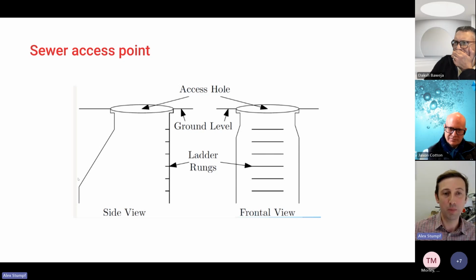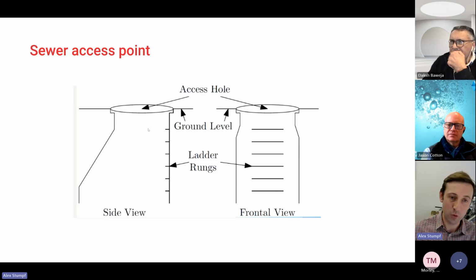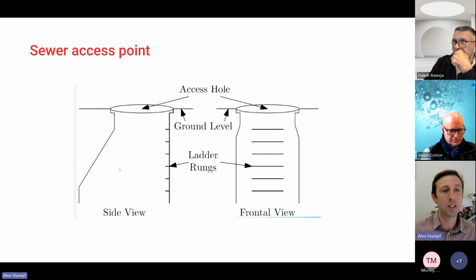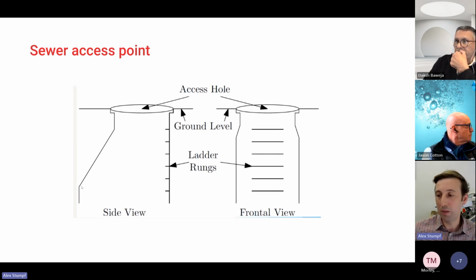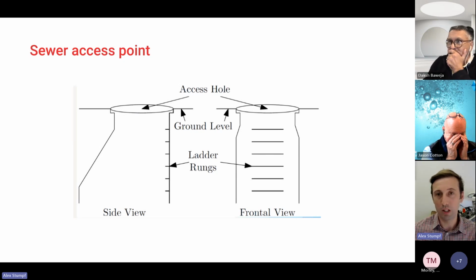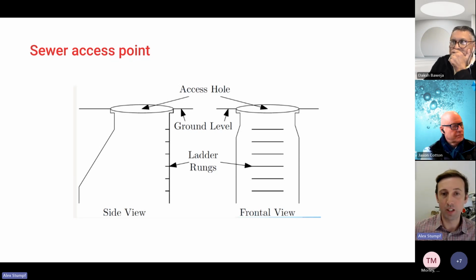So this is what a sewer access point typically looks like. You'll have the access hole, which is normally 600 mil diameter, and that section of the pipe will only be a short section typically. The reason is that if someone's going to enter into the hole, they don't want to be confined within a 600 mil opening. So they try to make this as small as possible, and then the pipe will extend outwards to around a metre, maybe 1200 on some of the larger sections. So it does vary. Again, for those older pipes, it depends how they did. If they cast it in situ, they've got the concrete truck and they had formwork and they made the pipe. For modern installations, it's pre-made, prefabbed, and they drop it in the hole, and you've got the pipe there ready to go.